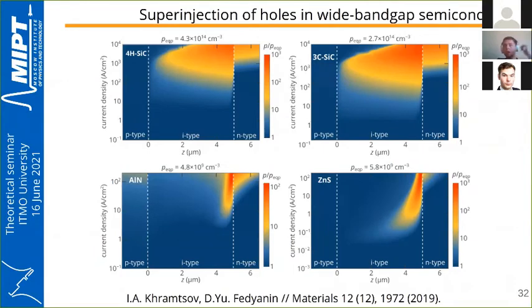In diamond, where there are problems with electrons, the superinjection effect of electrons exists. But in the case of other wide bandgap semiconductors, where there are problems with holes, the superinjection effect of holes allows injection of 2-3 orders of magnitude more holes than can be created in the p-type layer. It's the same as for diamond, but for holes in other wide bandgap semiconductors. Also, the holes tend to accumulate near the I-N interface, which is counterintuitive.